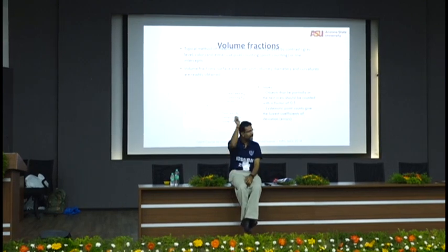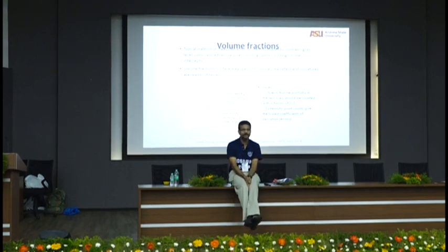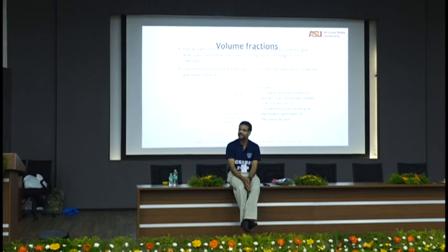So you throw a large number of random darts at this image, and finally, okay, I've thrown 1000, how many have stuck in the elephant? 400 in the elephant, 600 out of the elephant. The elephant occupies 40% of the image area, right? You do it enough number of times and statistically average it, don't you think you will get a right answer? It's as simple as that. So it's a very smart method. Instead of throwing darts, you just count points.